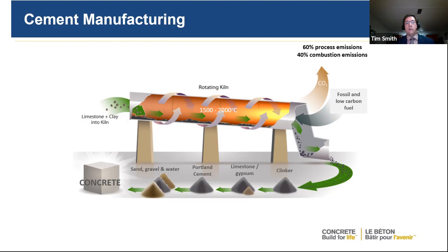The raw materials go in, they're heated at a very high temperature to produce the clinker. The difference is in general use cement, you take the clinker and you grind up to 5% limestone with the gypsum to create the Portland cement. What you do with general use Portland limestone cement is you grind up to 15%. Because they can't go over 15%, it's going to be around 12 and a half to 13. In the normal GU cement, they're at around 2 to 2.5, so that they don't go over 5%. So basically, you're putting in 10% more limestone, which reduces your CO2 output by 10%.